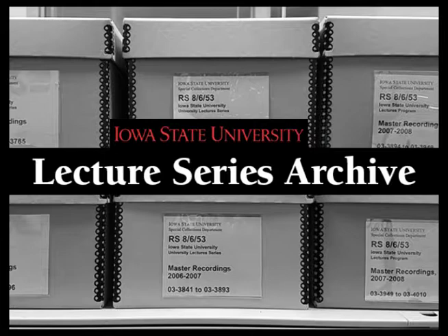So that was the request they came to us with, which is not an easy one to fulfill, because cartilage has very unique properties. It's very difficult to match the properties of cartilage. So with just organic materials alone, it's hard to do that. So we came up with this idea of this injectable nanocomposite, and we've shown that since it's injectable, since it's liquid at room temperature, and then when you inject it into the body, it immediately forms this gel nanocomposite. What that allows us to do is to be able to fill the cracks. So you can have different shaped cracks. If you start off with a material that's already solid, you can't fill cracks. But this way you can actually fill the cracks.